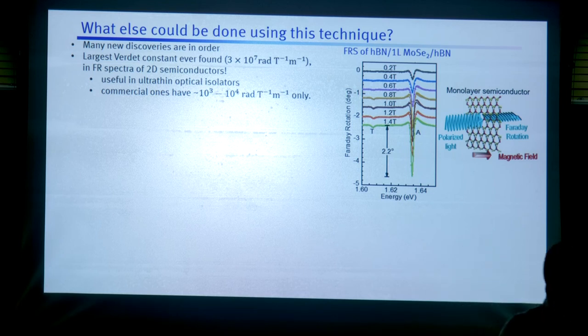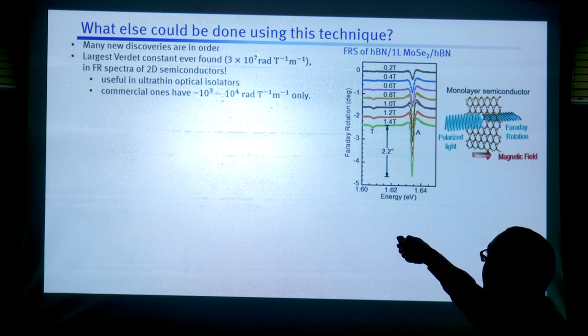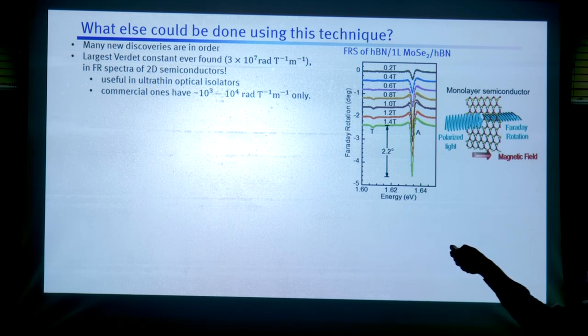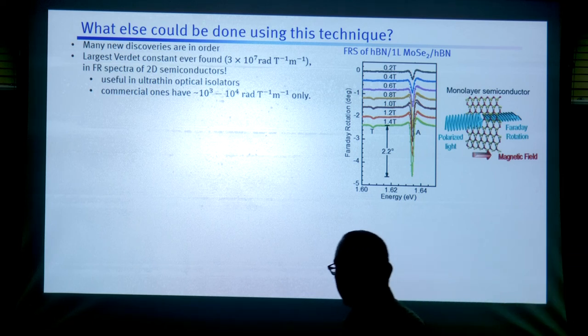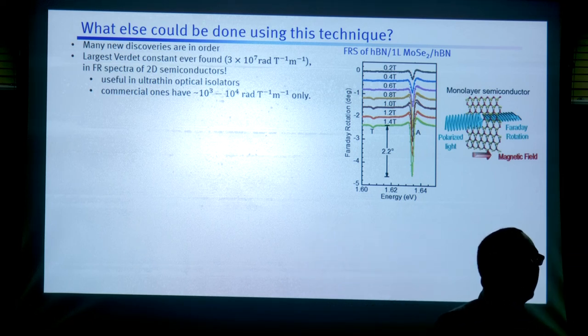One can imagine that you are able to rotate the plane of polarization by 2 degrees by passing light just through a single layer of material. If we compare this with other things available in the literature so far, everywhere we have numbers of the order of 10 power 3 or 10 power 4, but in this material it's 10 power 7. What is this number? This number is the amount of rotation per Tesla per meter length of the material. This is called the Verdet constant. So this is the largest that we have ever found in the literature.